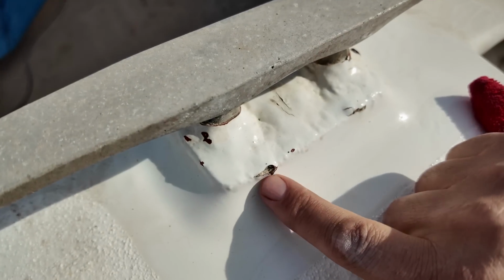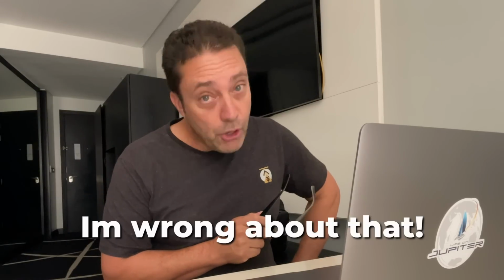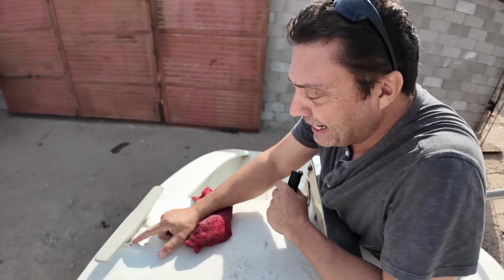The thing is, I had the impression that it was just some bubbling paint and that there was nothing actually happening or going wrong with the aluminium. It was just lifting paint, and I'm wrong about that. As I've removed the paint and seen under the bubbles, I can see that the aluminium is being pitted. Now this is on the deck area. This is not on the hull at all.